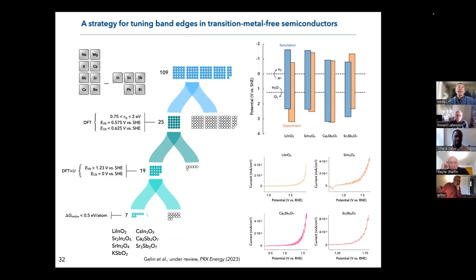And so because of that, we have focused the search on this type of design strategy, where we take elements on the right of the periodic table to make semiconductor with a small band gap, very good at absorbing solar light, and then mix them with elements on the left of the periodic table to be able to adjust their band gap. And doing so, you see we obtain many materials that actually can adjust the band edges in such a way that they will straddle the redox potential of water. So this is the general design strategy that we're applying now with our process in order to really expand the pool of semiconductor.